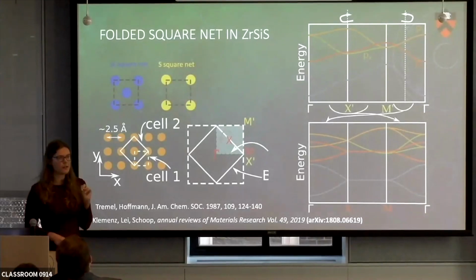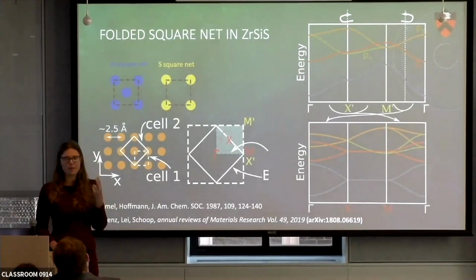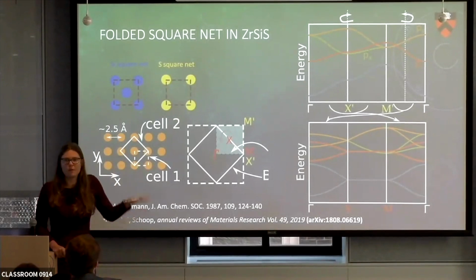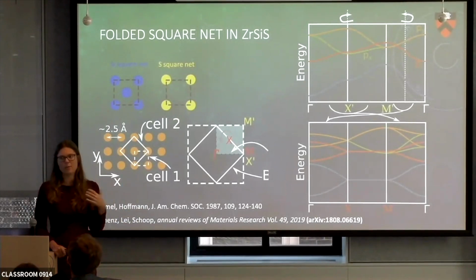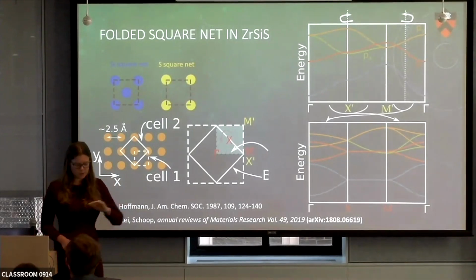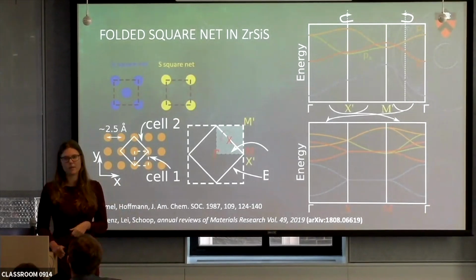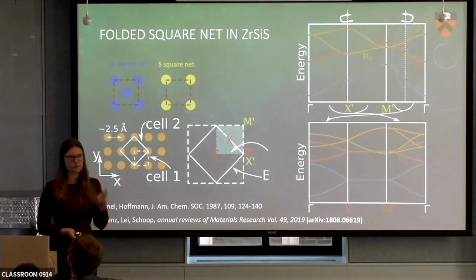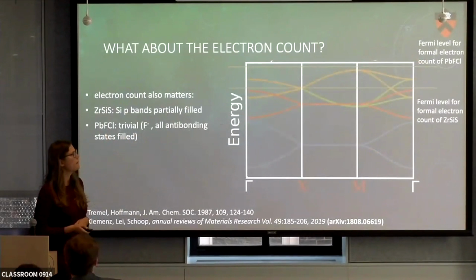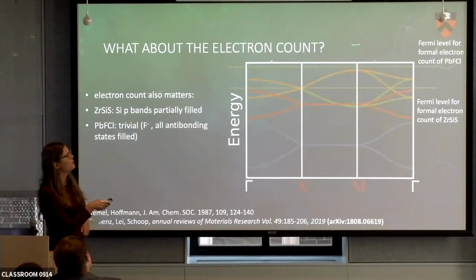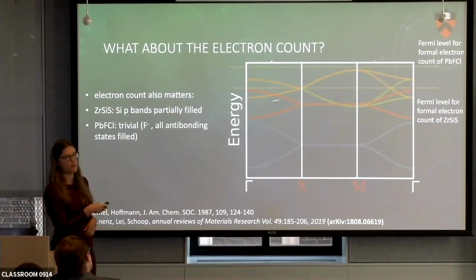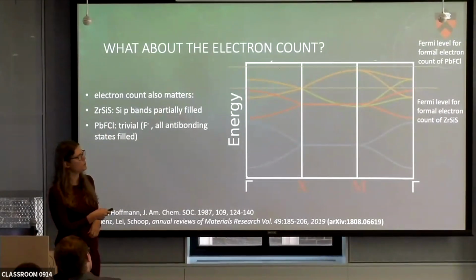Okay? So again, we need the two rules, because two chemically equivalent atoms by themselves won't do it, because the Fermi level can just be anywhere in the band structure. But if we combine this with a chemical delocalized bond that is present in the molecule, the Fermi level will be automatically at the crossing point in this band structure. Okay? So two simple chemical rules. Here we could be, if we have just a different chemical filling, no delocalized bond, just a normal ionic bond, our Fermi level would be up here, wouldn't matter, but because of a delocalized bond, we're here.